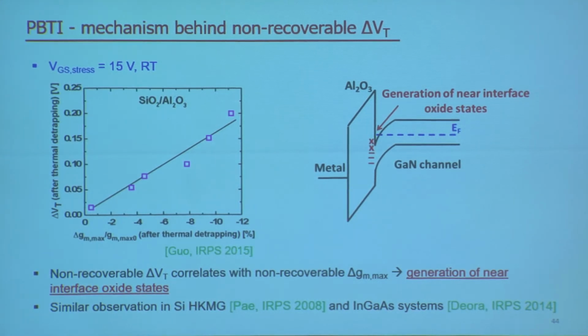And here is the correlation of this delta VT and delta GM, which are the two parameters that have permanent degradation for PBTI in high stress. And we see that they have a very good correlation, linearly correlated. And this suggests that the change of these two is from one single mechanism. And we believe that is due to the generation of near-interface oxide traps in the aluminum oxide. A similar observation has been made in silicon high-K metal gate devices, as well as in InGaAs systems with high-K dielectrics.